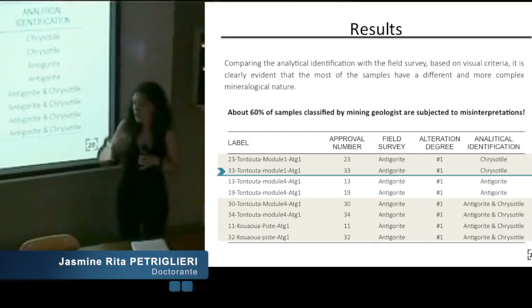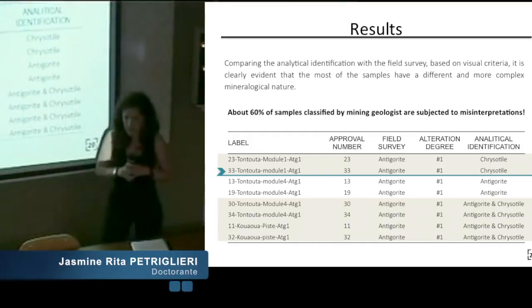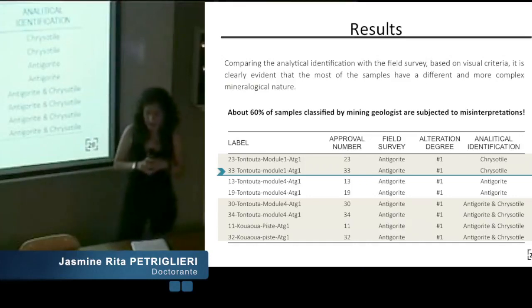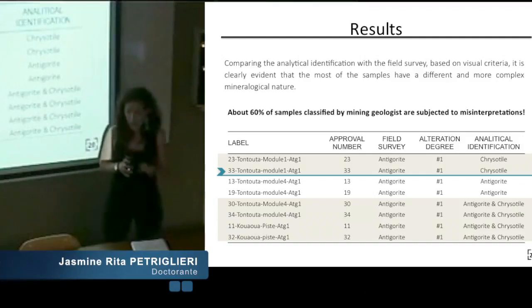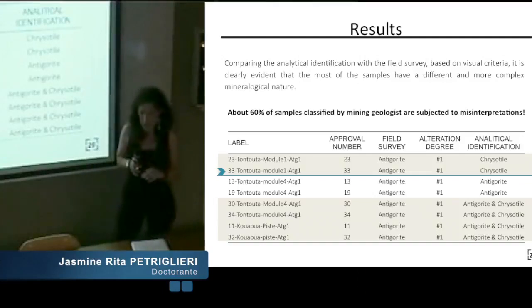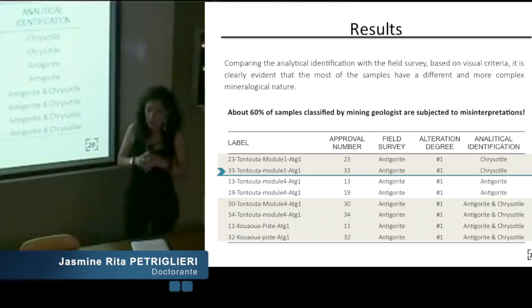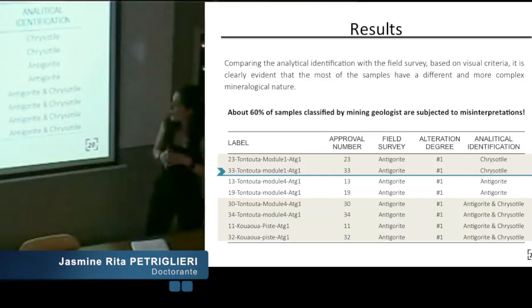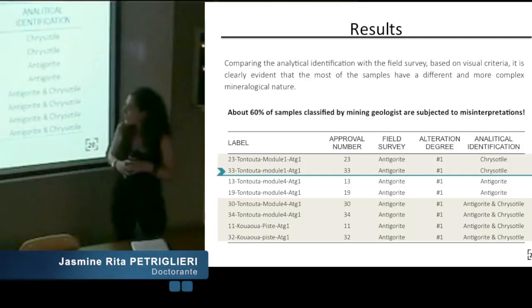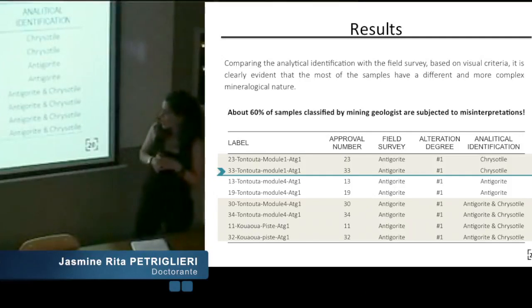The results show that about 60% of samples classified by mining geologists are subject to misinterpretation. Comparing the analytical identification with the field survey, which is based on visual and morphological criteria, it's clearly evident that most of the samples have a different and more complex mineralogical nature. I report the example in the table of some specimens identified by geologists of the mining company as antigorite,